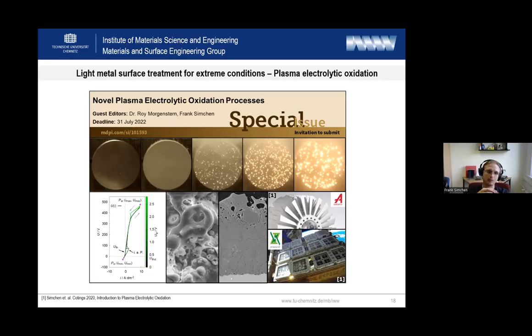So you don't, for example, need to be scared that you change the Wärmebehandlungszustand, the heat treatment state. The heat treatment state, yeah. So if you put a T6 aluminum alloy and apply this coating, afterwards you still have a T6 aluminum alloy. So the thermal influence to the substrate maybe exists, maybe detectable with scientific methods, but it doesn't play a role in this technological scale. These discharges are unbelievably hot and unbelievably tiny. So this leads to the funny result.